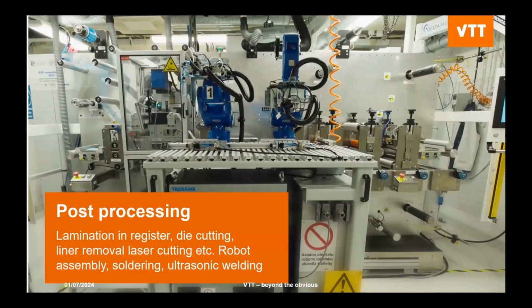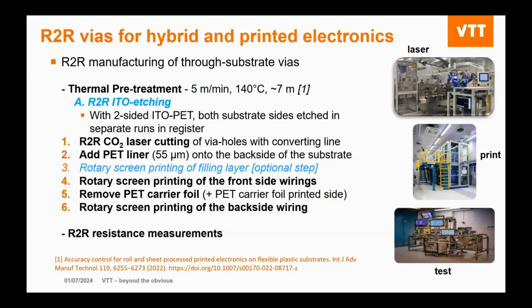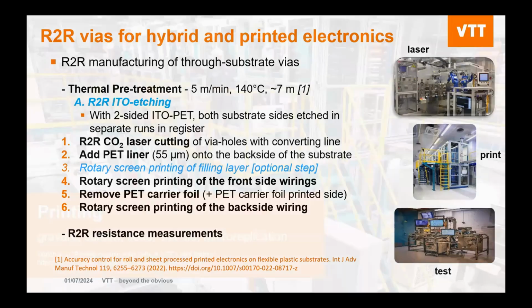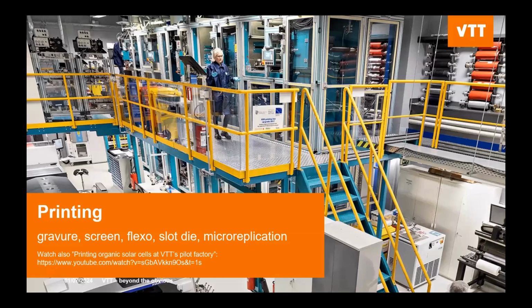And this is our CO2 laser right here. The reason why you want to add the liner is so that you don't get any fouling or ink seepage through the via holes. Of course, when you're doing sheet-based processing, you don't really think about this, but when you're using roll-to-roll processes, it's very important to consider. So after you add the liner, then you can go to your printing line. This is one of our larger roll-to-roll printing lines. And here you can see the printing unit would be on this far end, and then we have these large ovens that are spaced out sequentially. The reason why it's two stories is so that we can reduce basically the surface area of the device. If not, it would be outside the building.